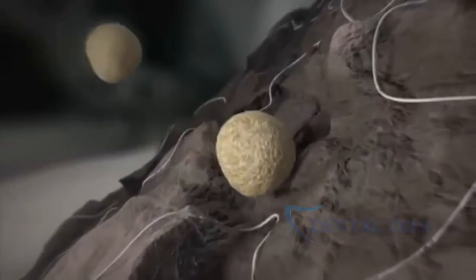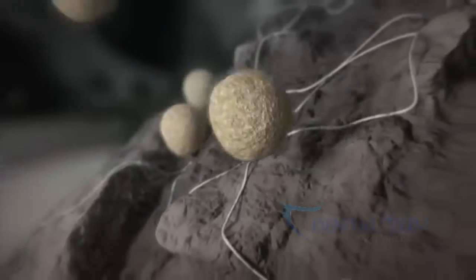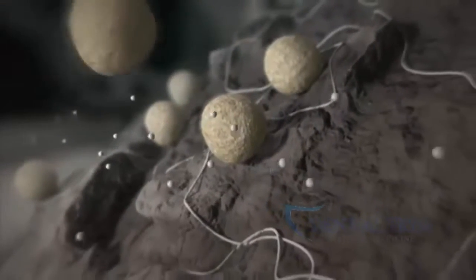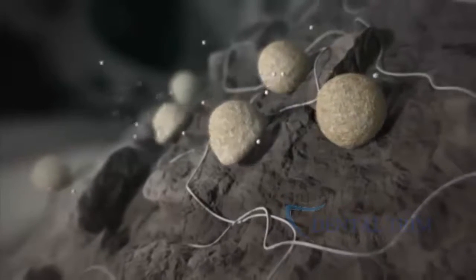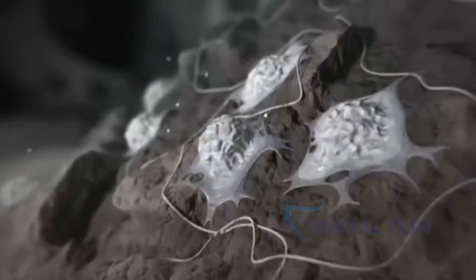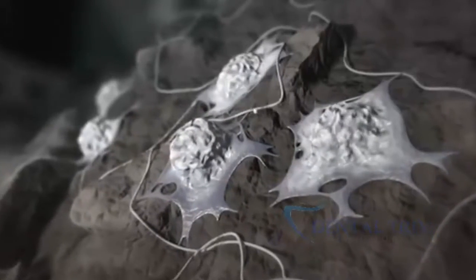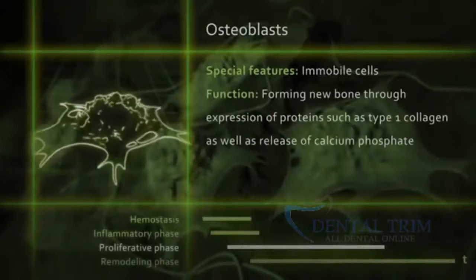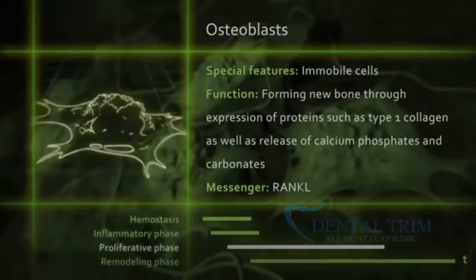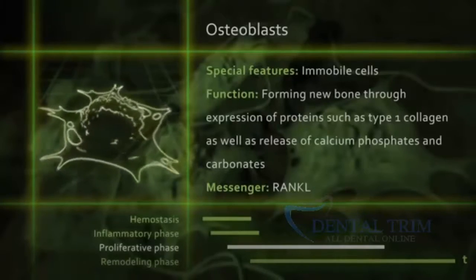Perivascular cells not only create new blood vessels — they also migrate toward existing trabeculae and to the implant surface, where they differentiate into new osteoblasts under the influence of BMPs from the dissolved bone. The adsorbed proteins such as fibronectin have a crucial influence on the attachment of bone progenitor cells to the implant surface.